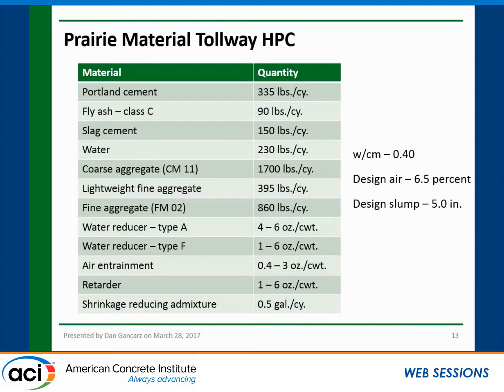It uses 3 aggregates, so we got a coarse aggregate. It uses lightweight fine aggregate for internal curing to mitigate shrinkage. We have a natural sand, various admixtures, including a half gallon of SRA.